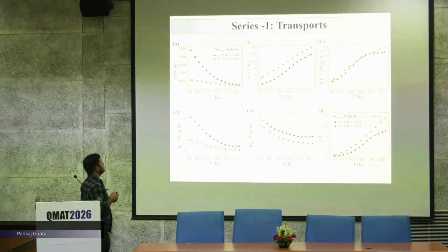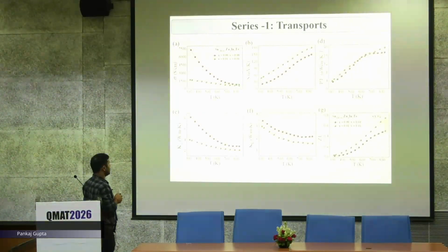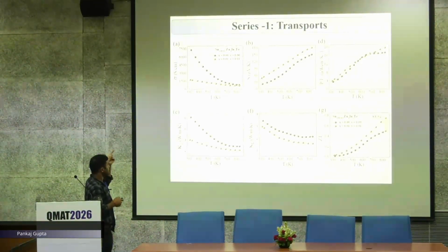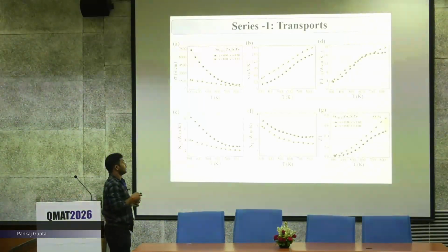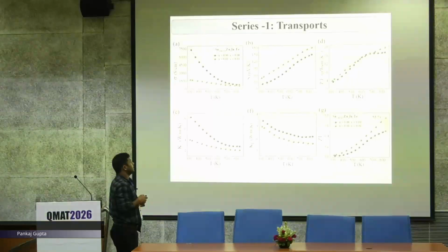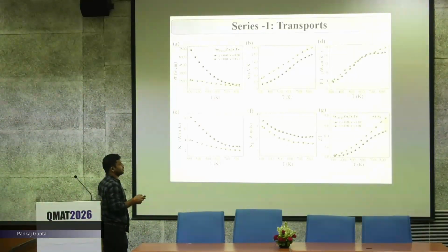So what is happening here with doping? Electrical conductivity is reducing a lot because of the heavy effective mass coming due to the indium, because of the high density of states, that is killing the mobility, hence it is going down. But at the same time, since the effective mass is very high, meaning the Seebeck is very high, and hence we are getting a power factor reasonably better than the pristine.